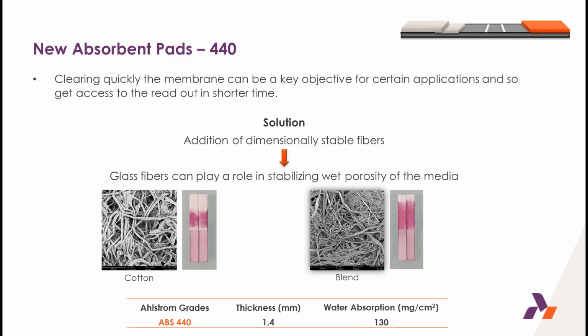However, for specific application, one major consideration associated with the use of the absorbent pads is to quickly clear the membrane, and so to get access to the readout in shorter time. That's the reason why we have decided to add dimensionally stable fibers, mainly glass fibers, to the basic cotton fiber structure in our new developed absorbent pad called the 440. This material quickly absorbs a higher volume of liquid and so limits the swelling commonly observed with only cotton fibers, as you can observe on both pictures of this slide. As a result, the drying of the membrane with this absorbent pad is much faster, and the line is better defined.